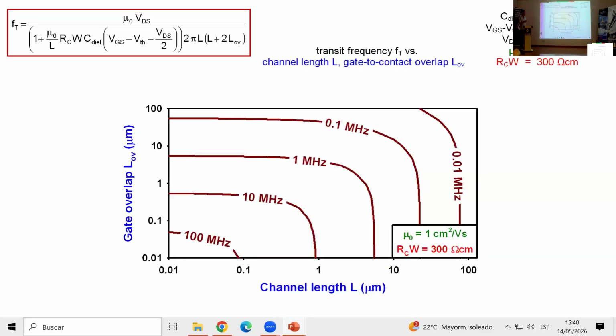And now, the only 2 parameters in this equation for which I have not made any assumptions yet are the channel length and the gate overlap. Okay, so purely dimensional parameters, physical parameters of the lithography that we use to fabricate the transistors. And so we see that in order to be able to achieve a transit frequency on the order of 10 megahertz here, it's immediately clear that we will succeed in that only if the transistor has a channel length that is smaller than 1 micron and gate overlaps that are smaller than 1 micron. Okay. If the lateral dimensions of the transistors are greater than 1 micron, we'll never be able to achieve a transit frequency of 10 megahertz for these parameters. Okay, that's essentially what we get from this plot.